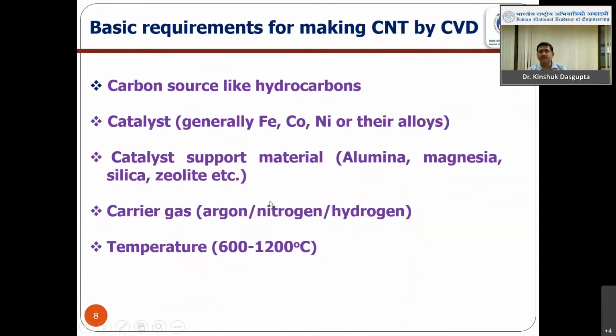So what are the basic requirements for making carbon nanotube by chemical vapor deposition? So we require a carbon source like hydrocarbons. We require a catalyst, generally transition metal catalyst or their alloys are used like iron, cobalt, nickel. And we require a catalyst support material because this catalyst needs to be dispersed, otherwise they will agglomerate, and once they agglomerate they cannot catalyze carbon nanotube. So generally alumina, magnesia, silica, zeolite, or we have used carbon black that are used.